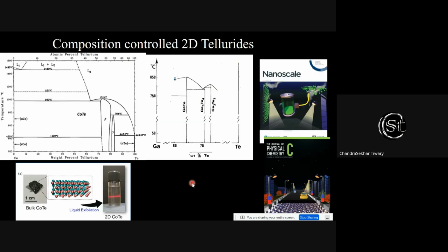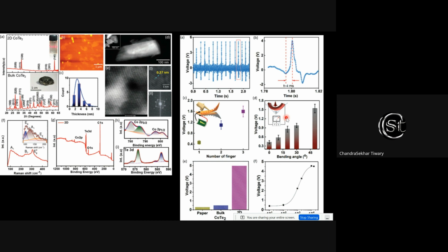Now, taking it ahead, we can also make 2D materials with a controlled composition, where we take certain elements, mix them together, heat them, and get the required phase. Once we get this crystal, we can exfoliate it at large scale production, and we can make good lateral size. Also, the thickness can be tuned, and such material can be utilized for coating on a substrate and used for energy harvesting. Cobalt telluride is one example which utilizes flexoelectric properties.